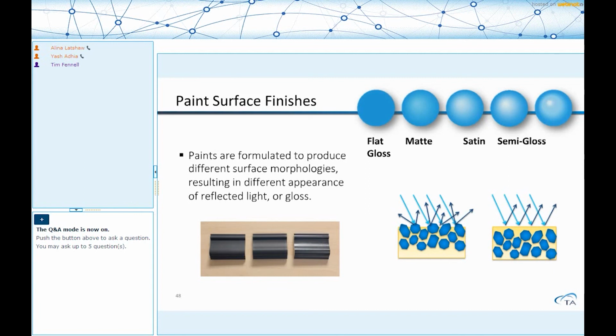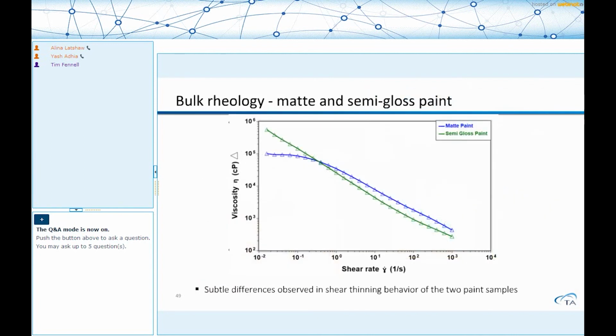One is, of course, the optical property, whether it's flat, gloss, matte, satin, or semi-gloss, so that's the amount of light. And so the question is, when you look at just the bulk flow properties, of course, they'll be slightly different. For example, when we've taken two kinds of paints, one matte and another semi-gloss, you can clearly pick out the subtle differences in the shear thinning behavior. The matte paint, in fact, shows a much more pronounced zero shear viscosity.